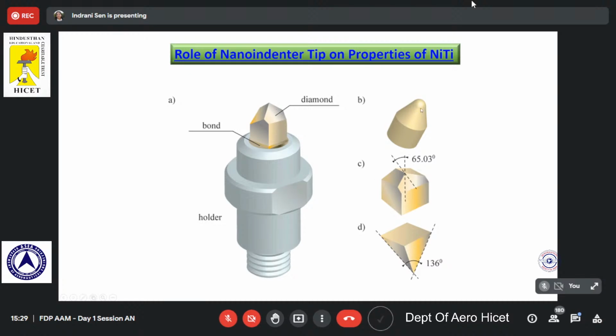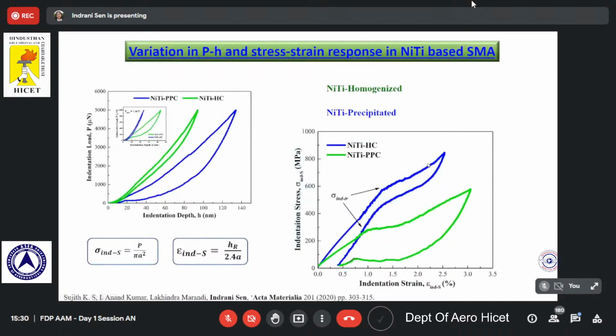Along with that, we have also taken a spherical indenter tip, which, as you can see, the tip is quite blunt. Why we use two different kinds of indenter tip is to make sure that there is not a significant amount of plastic deformation. We can still impose a very low amount of plastic deformation to figure out any differences in the pseudoelastic recoverability, if there is, amongst the homogenized condition as well as the precipitated condition.